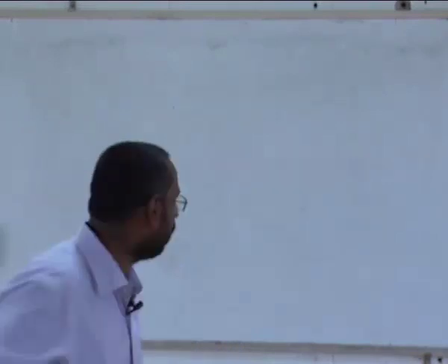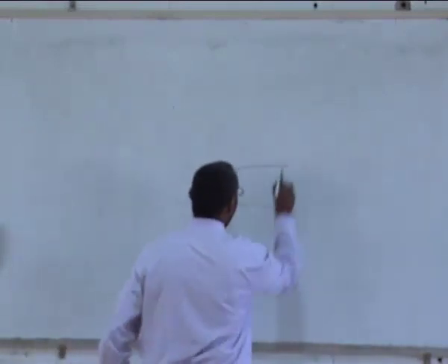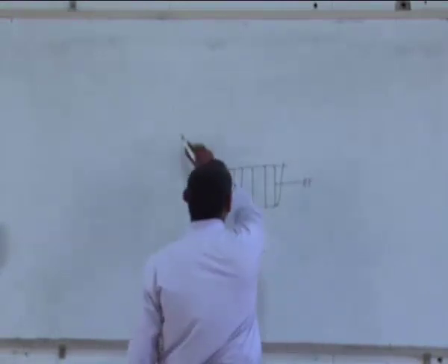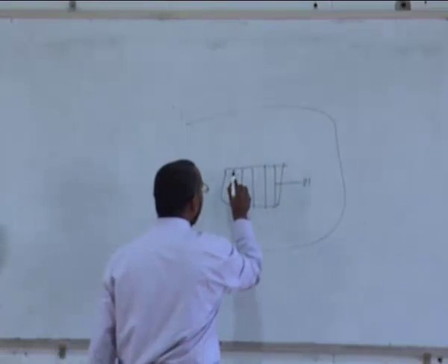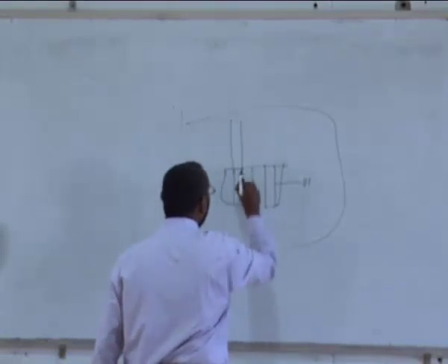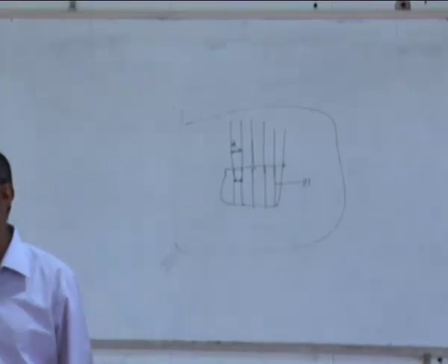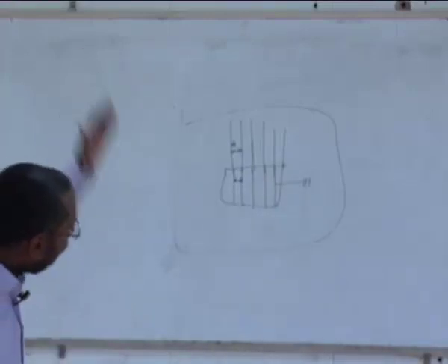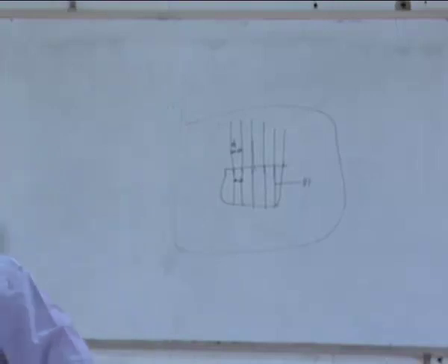So when you say matching, what she means is that the atomic planes have to be continuous across the interface. If I say a particle and I talk about a certain atomic plane, whatever it is, let's say the 1 1 1 plane, and if there is a matrix, and the planes in the matrix also have similar d-spacing, interplanar spacing, such that there is a continuity across the interface of the atomic planes, then we call it a perfect matching.